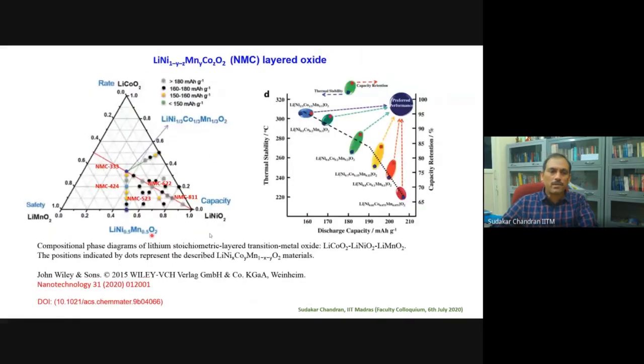And there are many such compounds that are being explored even today. Just to point out the complexity that is involved in deciding the right composition, you can see in this phase diagram, some of the important compounds that are known are highlighted. They are given names based on the ratio of the nickel to manganese to cobalt. For example, 4-2-4 means 40% nickel and 20% manganese and 40% cobalt, like that. So there are many, many different compositions explored.